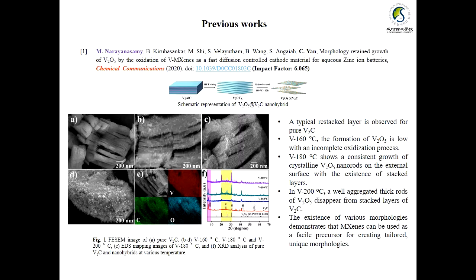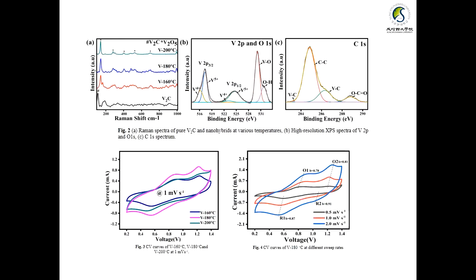demonstrates that MXene can be used as a facile precursor for creating tailored and unique morphology. Here in the XRD also you can clearly see that for the 180 degrees centigrade MXene, the V2C peaks are combined with the V2O5 peaks. In the Raman spectra and XPS analysis, in the Raman spectra we can see that at around 180 degrees centigrade the mixed state of vanadium as V2O5 and V2C is present, whereas at 200 degrees centigrade we could see that the V2O5 peaks are predominantly present, and in the XPS analysis we get to know that